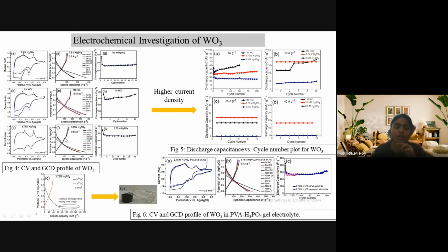And here we faced one issue, that there was continuous discharge after a few cycles, say after 30 to 40 cycles. Here we can see it was quite prominent in the case of HCl. As we are using aqueous electrolyte, in aqueous electrolyte a side reaction or splitting of water can occur.